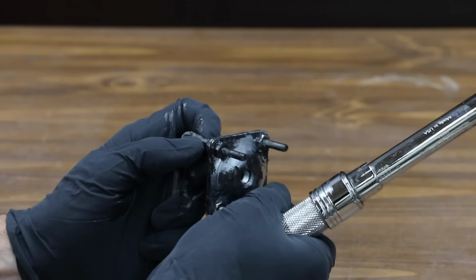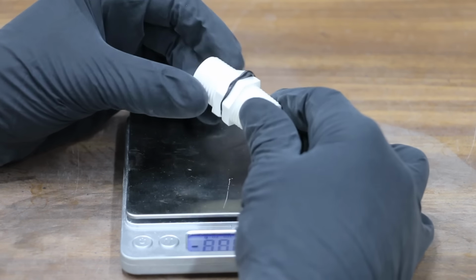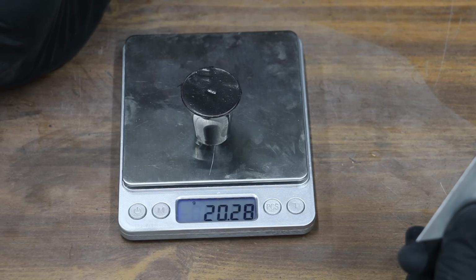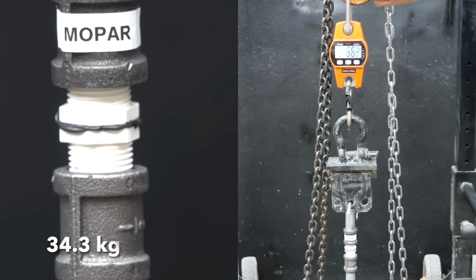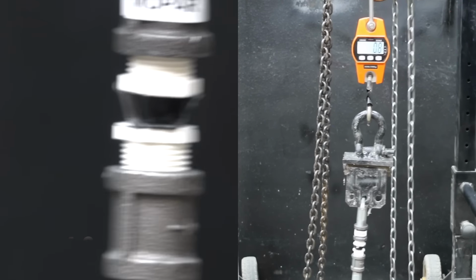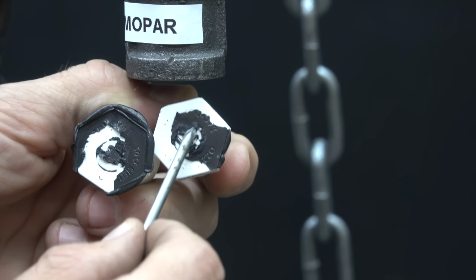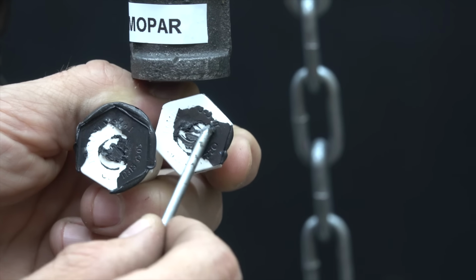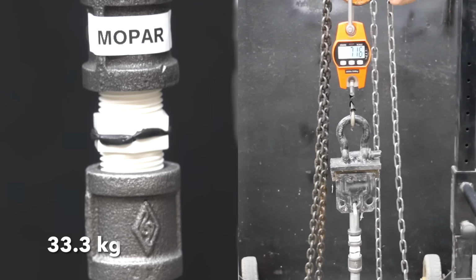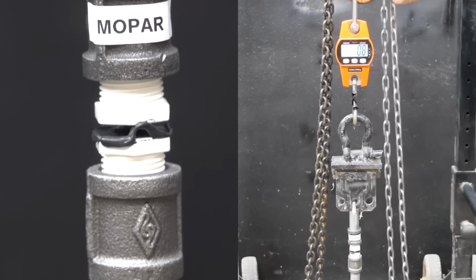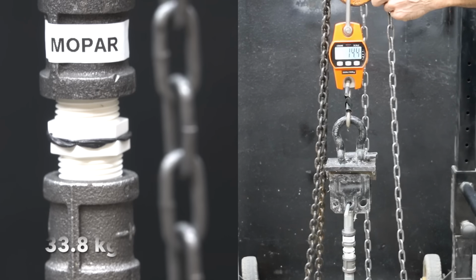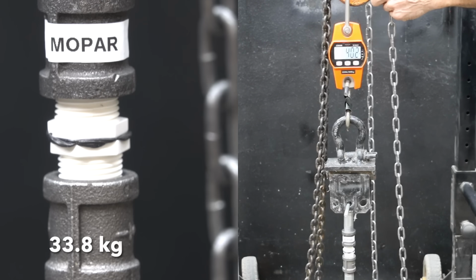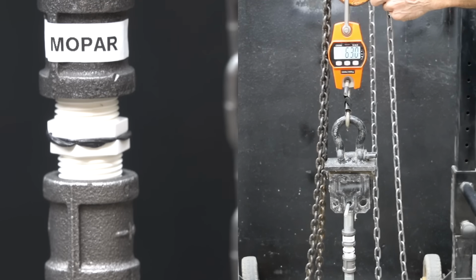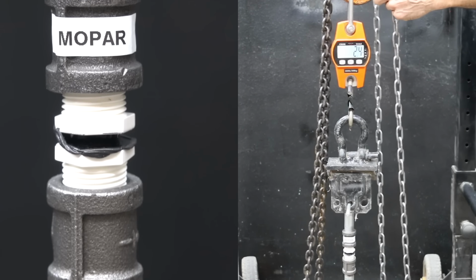Apply a single bead to one surface. Assemble and allow to cure. And the MOPAR weighs 20.28 grams. And the MOPAR performed the best yet at 75.6 pounds in the first test piece. There's quite a bit of uncured gasket maker in the center of the PVC end cap. And the second test piece performed very close to the same as the first one at 73.4 pounds. And the third test piece once again proved to be very consistent in performance at 74.6 pounds. So the MOPAR RTV gasket maker has the best tensile strength yet.